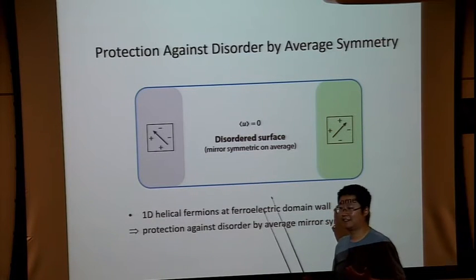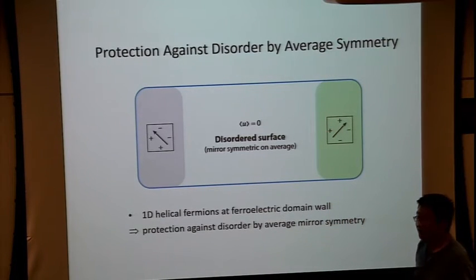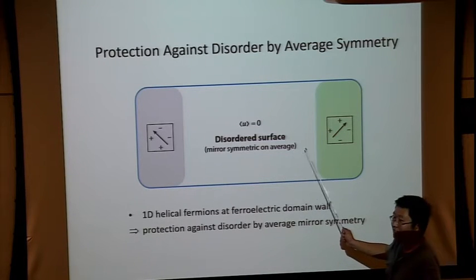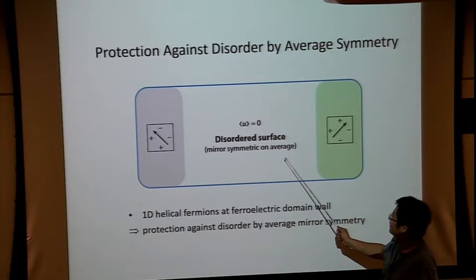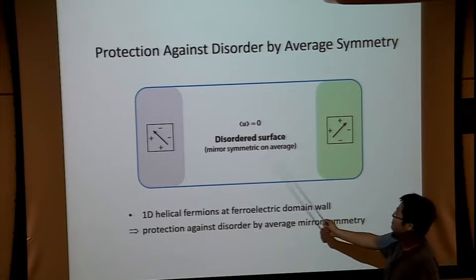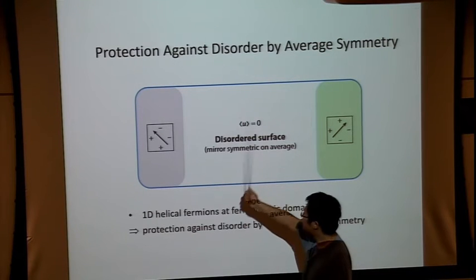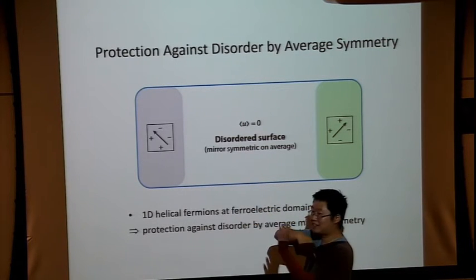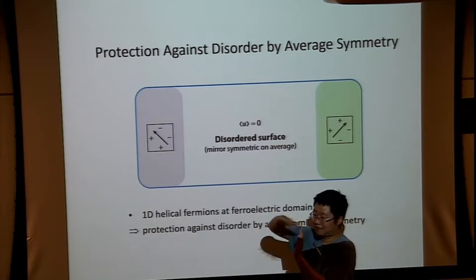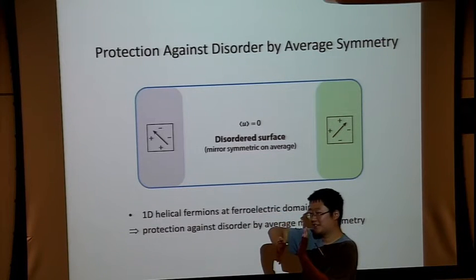That's not possible. What happens if you just put vacuum instead of the disordered surface? Using this argument to show that there has to be a conducting path in the disordered surface, it has to be non-localized. If I just replace it by vacuum, which part of the argument breaks? Oh, then what happens is that there's a side surface, so the top surface has to connect to the side surface.